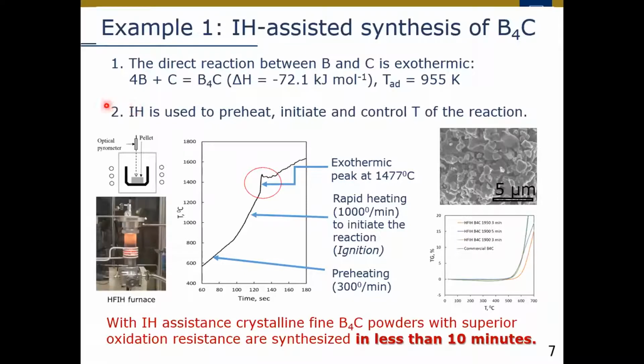And the second idea is to control the reaction precisely. I used induction heating to preheat, initiate, and control the temperature of the reaction. The experimental setup is shown here. It's very simple. And on this graph, I show the temperature profile during the reaction. This is temperature and this is time. Please pay attention to the time scale here.